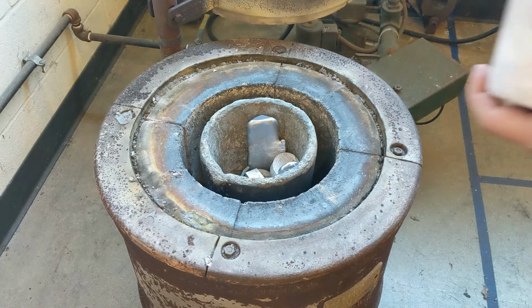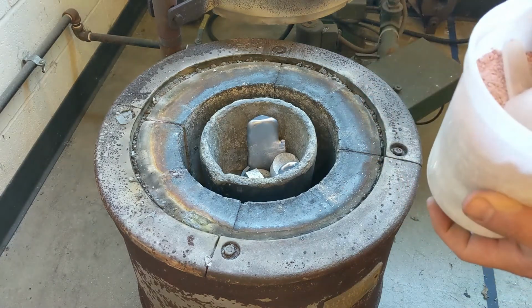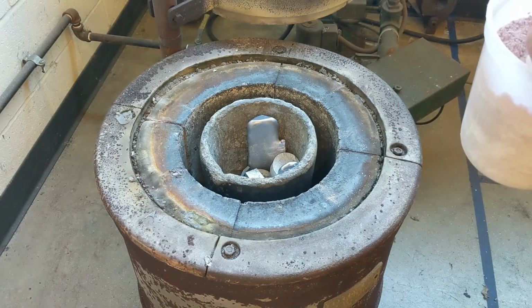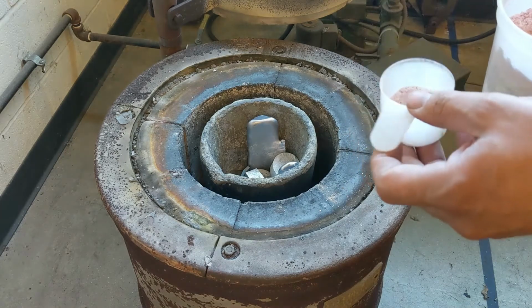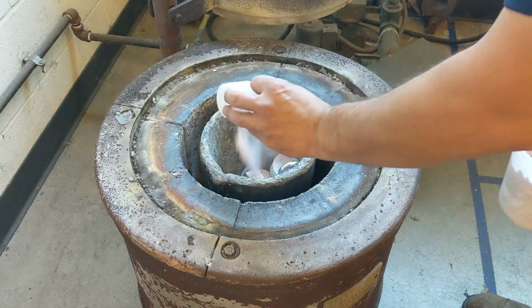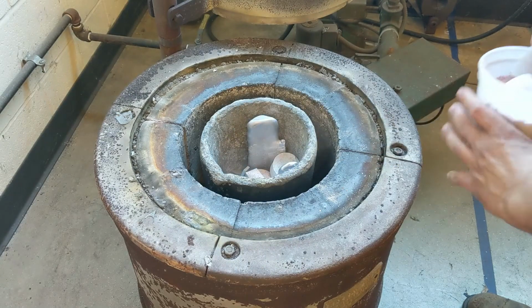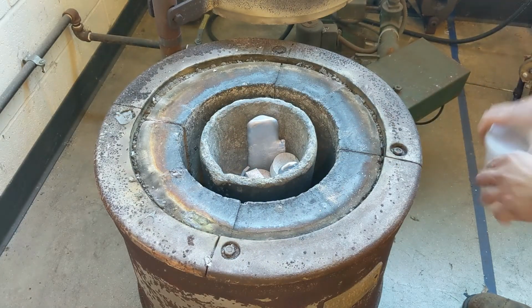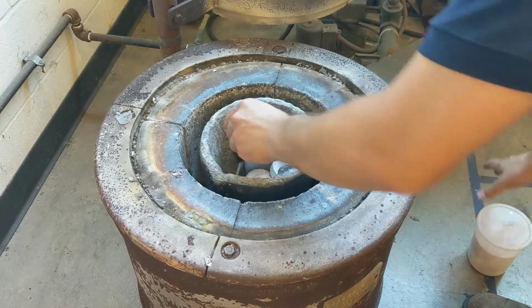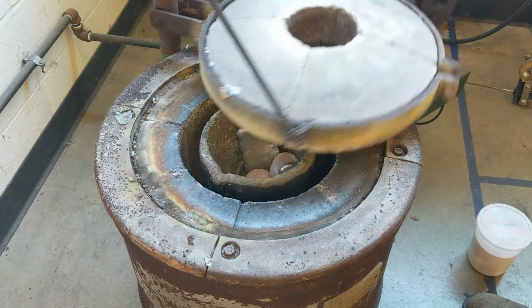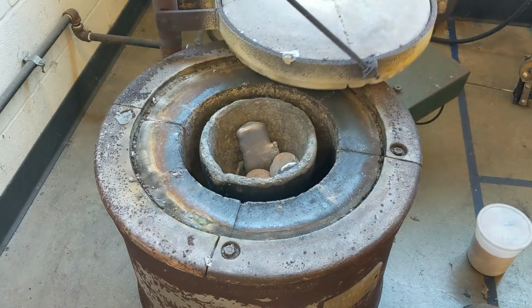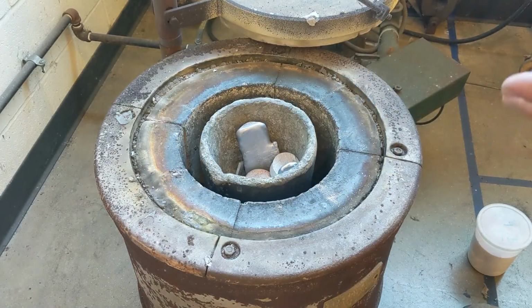And so I have here a powdered flux, and this is really not that much different from the flux that was on the electrodes that we welded with in last week's lab. I'll add that flux and make sure it goes to the bottom of the melt. I'll close this furnace and ignite the gas. Flow of compressed air and natural gas is going to swirl inside here. It's going to heat up that crucible and get us up to our necessary melting temperature.